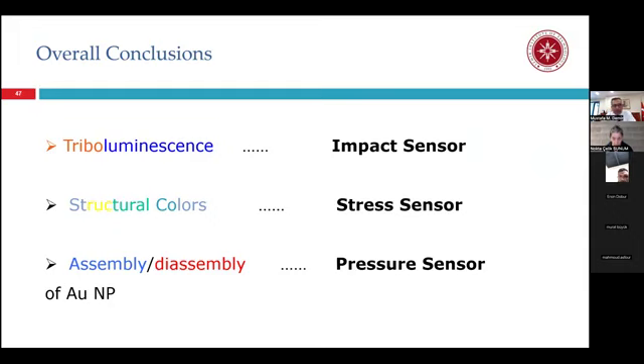Then I want to make an overall conclusion. In the last 45 minutes, okay, I showed you 3 different mechanical sensor systems, 3 different pigment systems, say. One was triboluminescent material. We mentioned red and blue types of triboluminescent material with different organometallic chemistry, and they can be used as impact sensor materials. The second one was structural coloration using polymer and silica colloids. We succeeded in obtaining different colors, and they can be used as stress sensor materials. And for the last part of the talk, I showed you the assembly and disassembly of gold nanoparticles, which have entirely different colors, and they can be used as pressure sensors in polymeric systems.